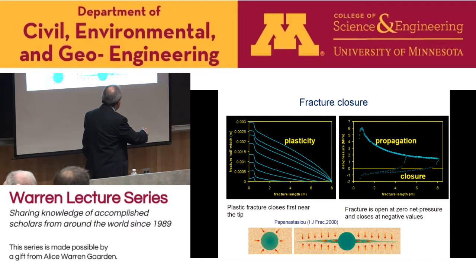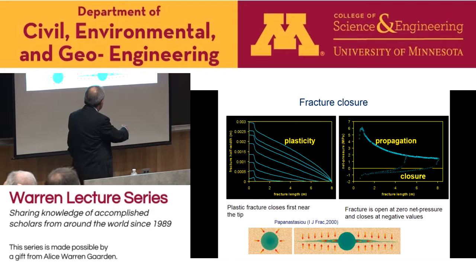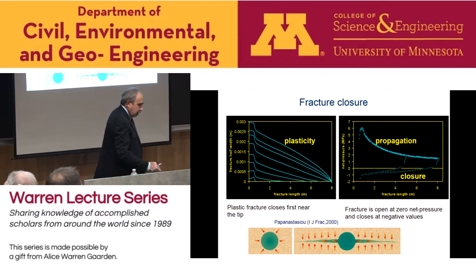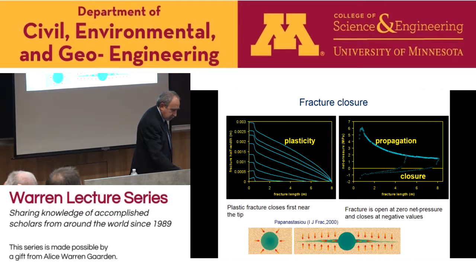And also the same pattern when we reach a longer fracture, again, in the same area here. Which means that if we take that the fracture is closed for this value here, we'll underestimate the closure stress. And as a result, we'll have a discrepancy later when we design the large hydraulic fracturing operations.